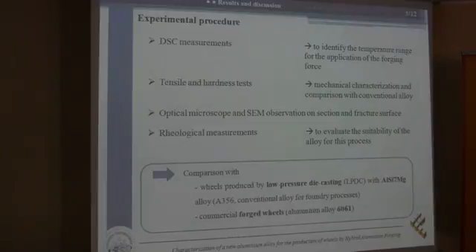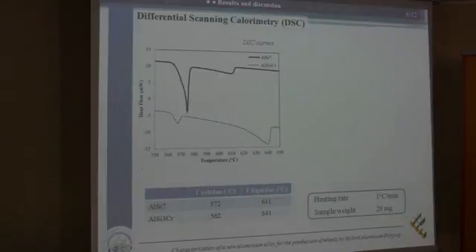technique. The experimental procedure: first of all, we perform these measurements to identify the temperature range for the application of the forging pressure, then mechanical characterization and microstructural observation with conventional techniques, and finally we perform also rheological measurements to better understand the suitability of this material for the process. The results will be compared with typical values of cast wheels and forged wheels. So, from the DSC curves, it was possible to calculate the solidus and liquidus temperatures and the values are shown in the table.